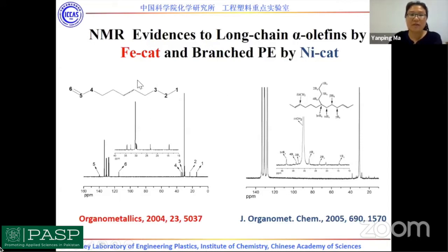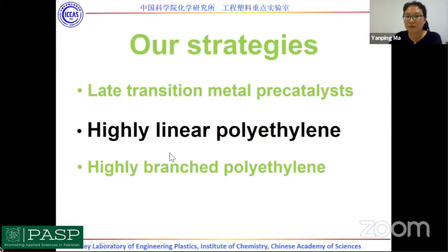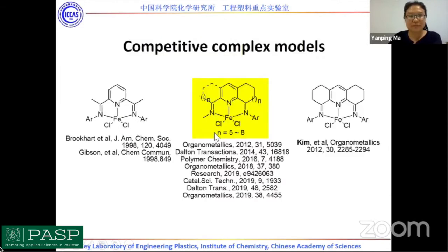So in the next part we will go into detail on these two polyethylenes. First I will introduce the highly linear polyethylenes, mainly focusing on the iron catalyst. Based on the skeleton structure reported by Brookhart and Gibson in their early work, we developed many kinds of iron catalyst. Especially, I highlight here the ring-fused catalyst. The ring fuse can be 5 to 8 membered rings and can be from one side and from both sides. It's an interesting catalyst.